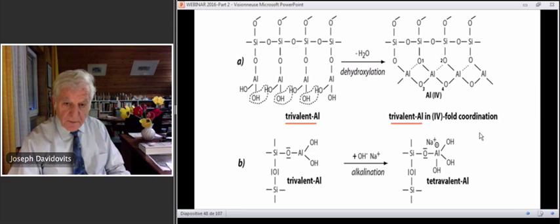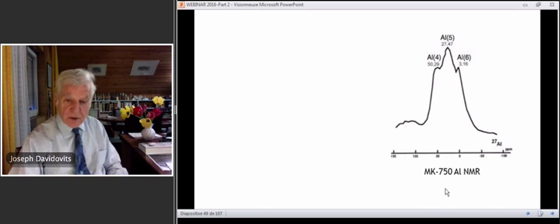Don't mix up. If we do it with a different representation, we have the SiO polysiloxo chain and the side groups. We have trivalent aluminum, and here alkalination. In alkaline medium, the aluminum is changed from trivalent to tetravalent, chemically speaking. We have aluminum covalently bonded to OH, OH, OH, oxygen, and the sodium is equilibrating the fact that the aluminum has got a negative charge. So it is tetravalent aluminum that is also tetra-coordinated. So don't mix up.